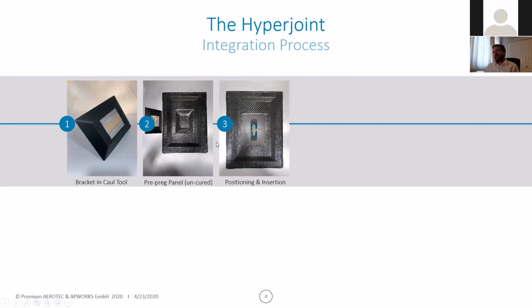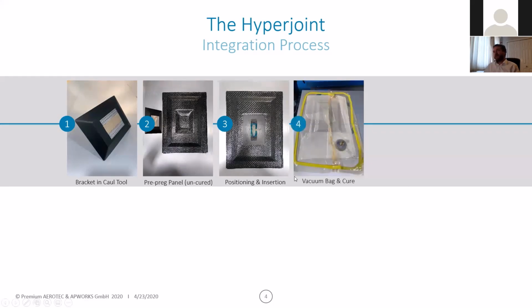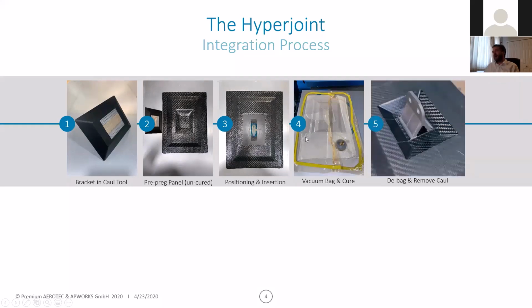In this case, this was done with a hand lay-up. Vacuum bagging as normal. Of course, you've got to accommodate the tool. So in this case, there's a small pleat in the bag, which you would position to try and minimize the risk of the bag bursting. You often have pleats anyway on the bag because of various other tools that are involved in the process. You're vacuum bagging, you're putting it in the autoclave or the oven, and then afterwards, you remove all this stuff after it's cured, and you've got something which is essentially a hybrid part.